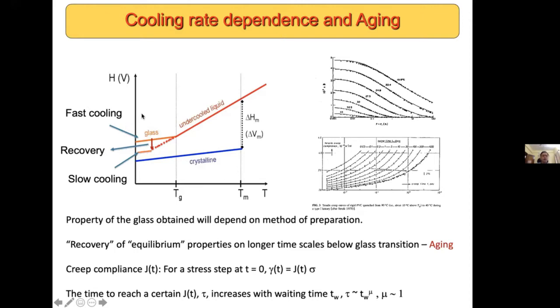However, real glasses are not in equilibrium, and if one waits longer, sitting at some temperature below the glass transition, one finds that there is a very slow process of time evolution, which is called aging, and there are other names in particular contexts, where one recovers what one might expect by extrapolation to be the equilibrium property of the liquid within limits, because the time scale that one can in fact wait is not unlimited.